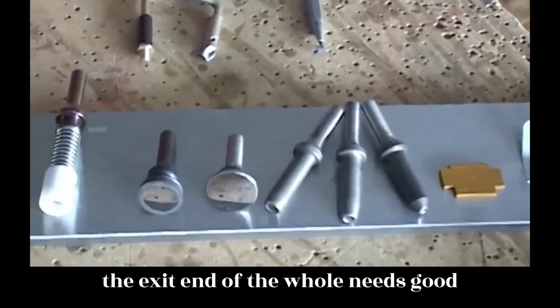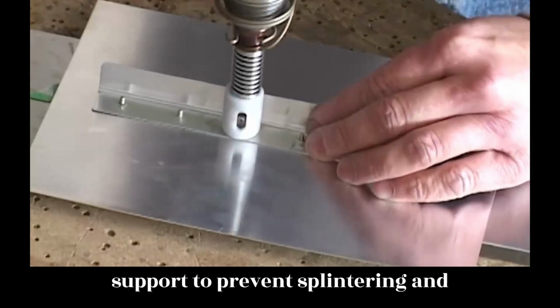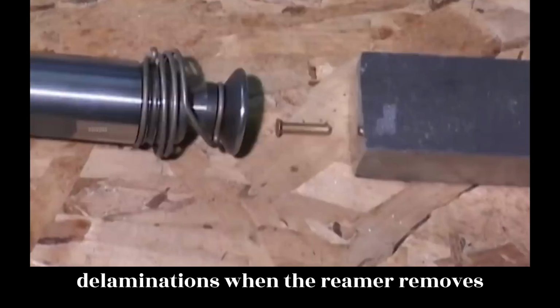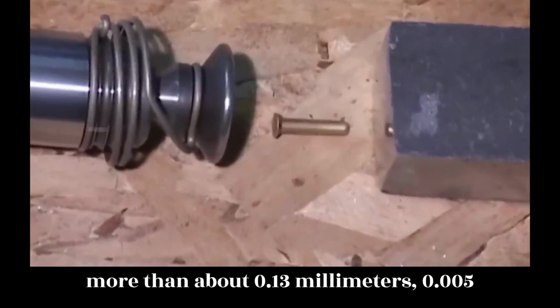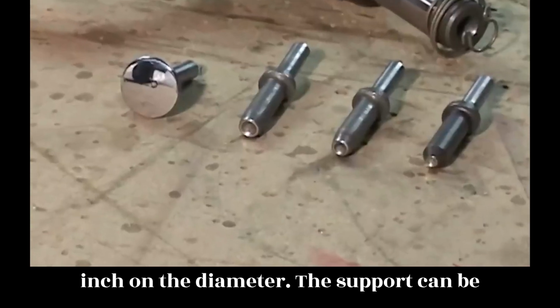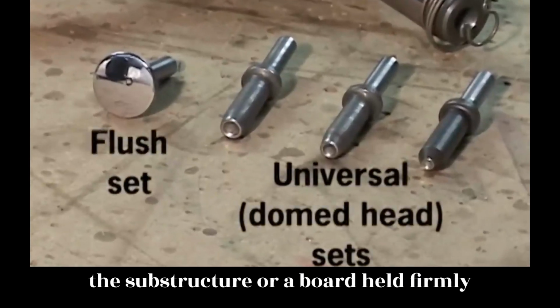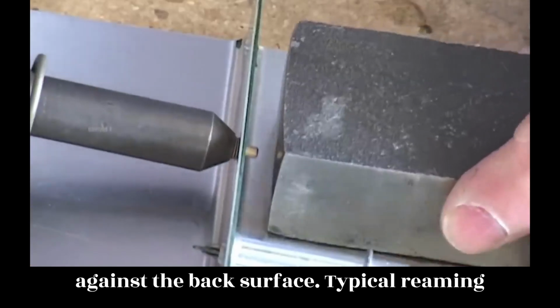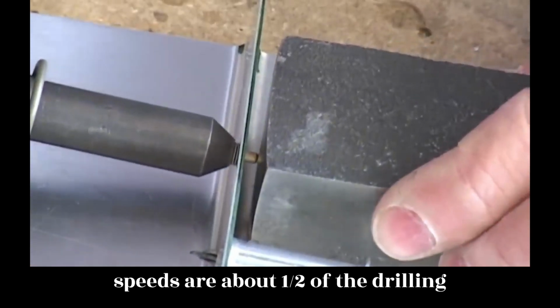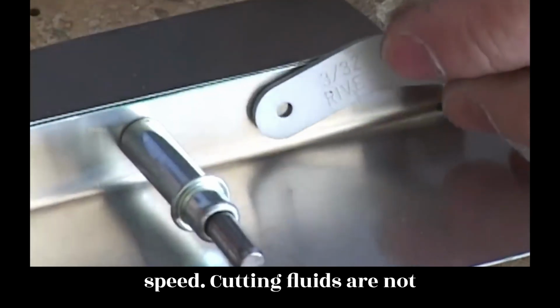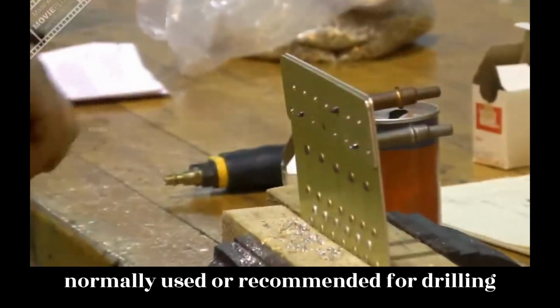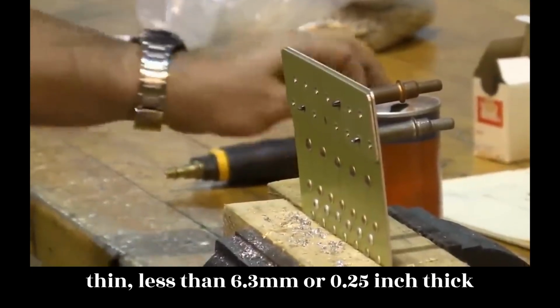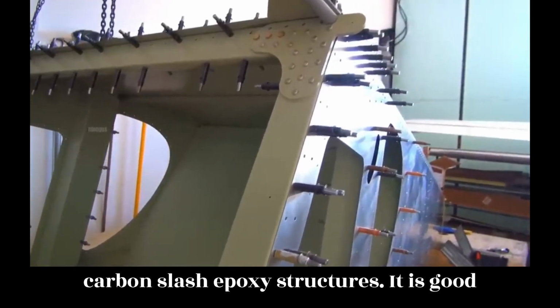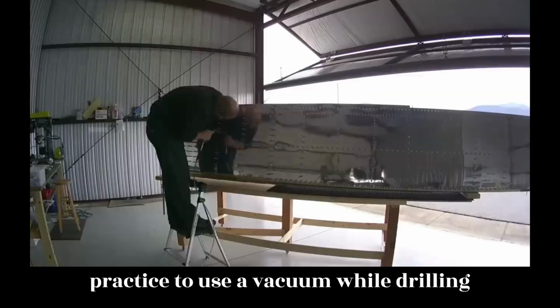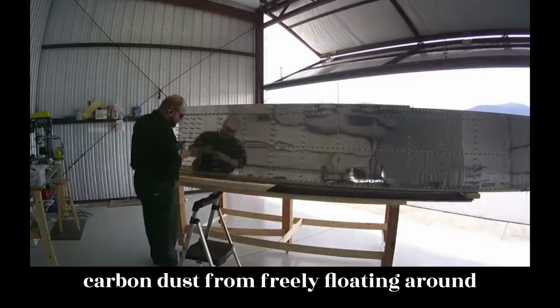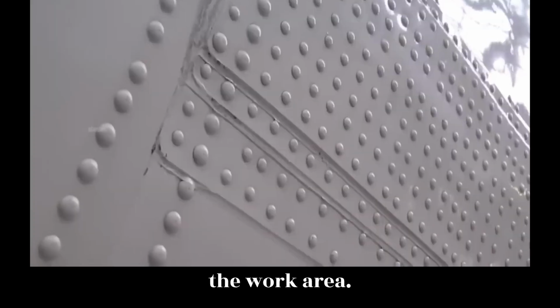In addition, the exit end of the hole needs good support to prevent splintering and delaminations when the reamer removes more than about 0.13 mm, 0.005 inch, on the diameter. The support can be the substructure or a board held firmly against the back surface. Typical reaming speeds are about 1/2 of the drilling speed. Cutting fluids are not normally used or recommended for drilling thin, less than 6.3 mm, or 0.25 inch thick, carbon/epoxy structures. It is good practice to use a vacuum while drilling into composite materials to prevent carbon dust from freely floating around the work area.